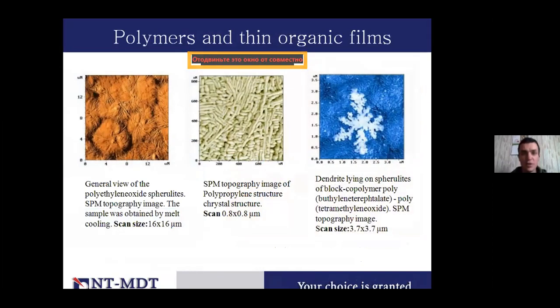Okay, and here you have some example of polymer study and organic film, just to understand that AFM is also applicable to soft material and not only to hard material, some semiconductor film. You can see here some images of different types of polypropylene, polyethylene oxide, spherulite sample, and some copolymer with different scan sizes, from 15 micron down to 1 micron and 5 micron. You can see different structure, and the sample is much softer. In that case, we need to apply some more gentle techniques, which is not contact measurement, but semi-contact, tapping mode, or non-contact operation, when the interaction force is very, very low. It's just to avoid any kind of interaction and deformation of the surface by the tip.